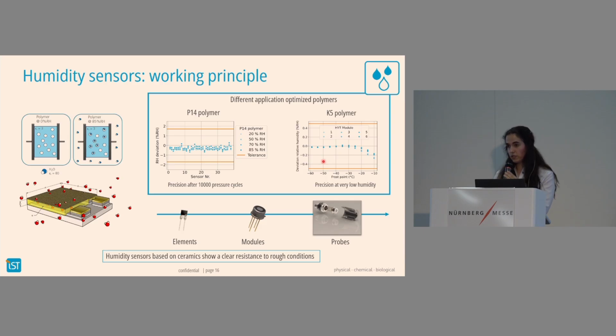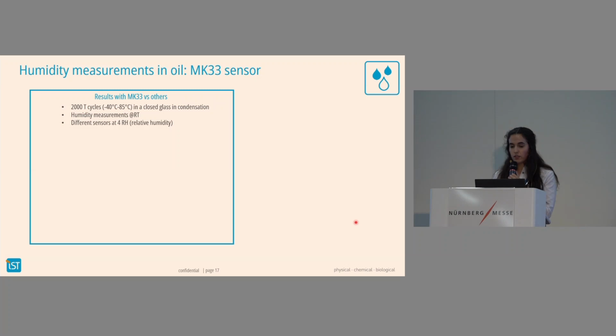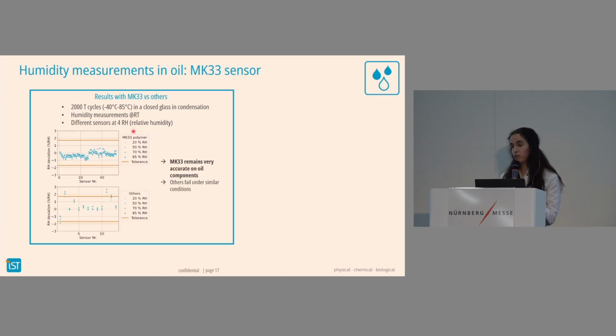For humidity, as for the previous cases, we can offer this in the form of an element, in the form of a module, that means with integrated electronics and calibrated, or as a probe that is already ready to be installed in the final application. And when we are talking about tough or rough conditions, the MK33 is the one polymer that we have developed that has shown over the years that it is quite robust. So the first measurements or results that I'm going to be presenting here are measurements after a temperature cycle between minus 40 and 85 degrees, and then humidity measurements at room temperature.